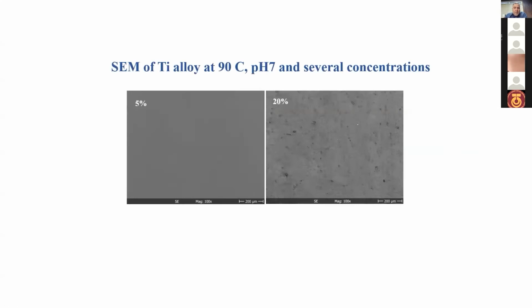Also, the scanning electron microscope for the titanium alloy after this test shows that there is no significant effect and no traces, no defects on the surface of this alloy after this test. Some traces of the corrosion after electrochemical test at the 20%.